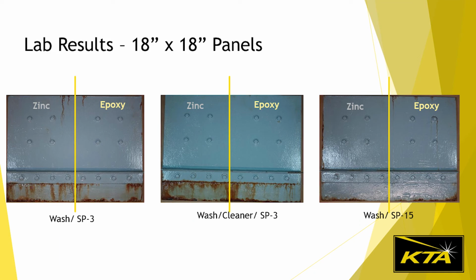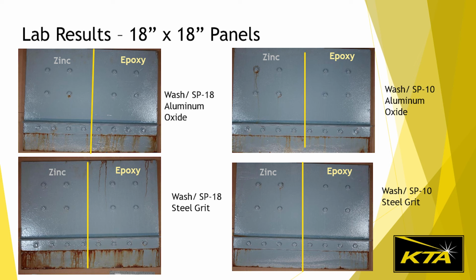They range from SP3, power tool cleaning, to an SP10 near white metal blast. The program explored the effectiveness of spot epoxy systems versus spot zinc systems. And each SP10 system received full organic zinc, full epoxy midcoat, and full urethane top coat.